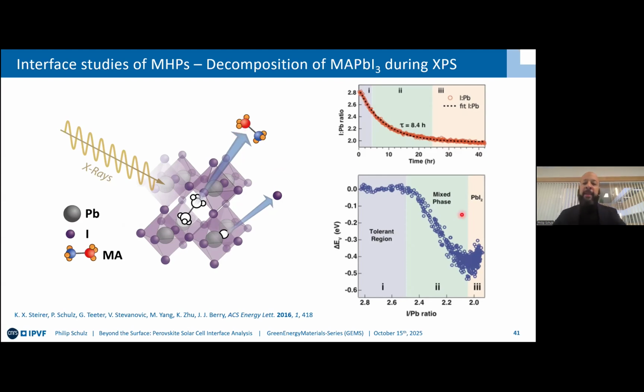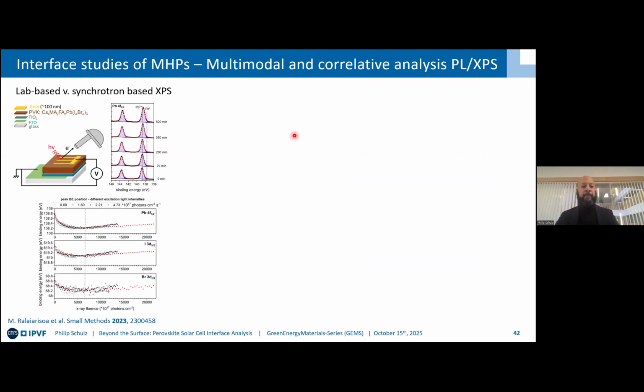So far, the position of the valence band maximum did not seem to be affected by this a lot, very likely due to Fermi level pinning. And it speaks volumes to the care you need to take while doing this measurement. And in the past couple of years, we were increasing our understanding of how to treat these samples.